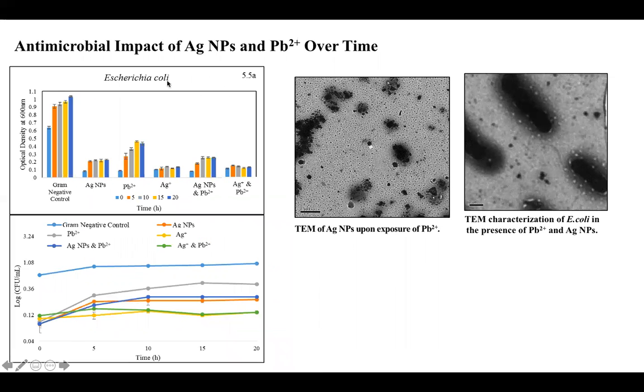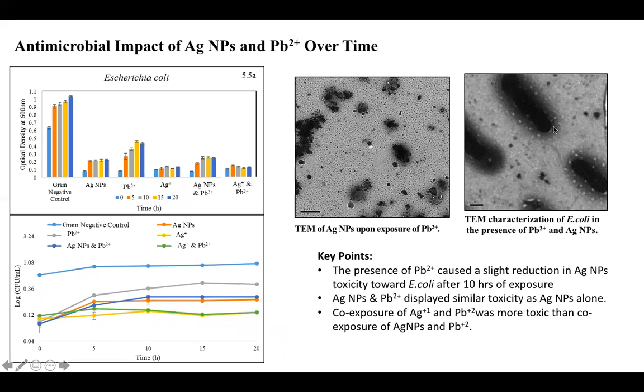All right, and then our final one, looking at silver nanoparticles and lead in the presence of E. coli. So for this one, again, we don't see that cell broken down as much, but we can see based on that E. coli structure that these nanoparticles are close by and they're able to attach to the surface of these bacterial strains, even in E. coli. So it takes a little bit more to break it down, but it is causing some type of reduction in growth and change in that structure. So again, we can see that in comparison to these three, there's a change in the different growth areas that we see.